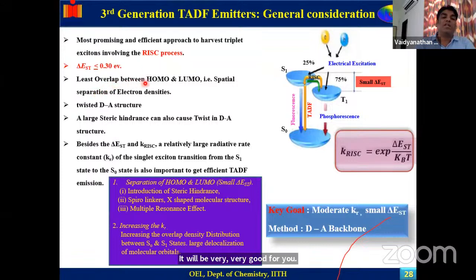We should have the least overlap between HOMO and LUMO. That is, spatial separation of electron density is necessary. That is only possible with a twisted donor acceptor structure, and large steric hindrance can also cause a twist in the donor acceptor structure. There are two things which we need to concentrate on: separation of HOMO-LUMO, to get a small delta EST value, and introduction of steric hindrance, spiro linkers, X-shaped molecular structure, multiple resonance effect. So you have B, N, O, S, etc. That can also create this type of small delta EST value.